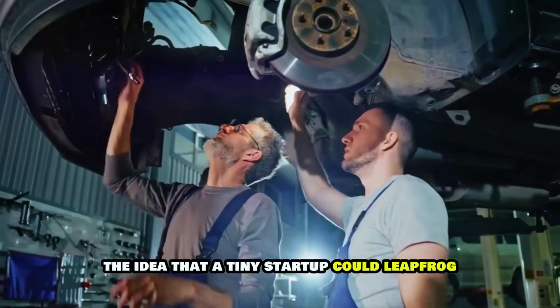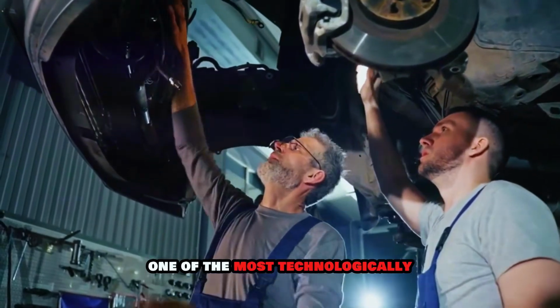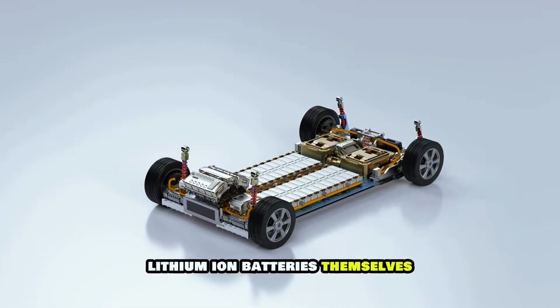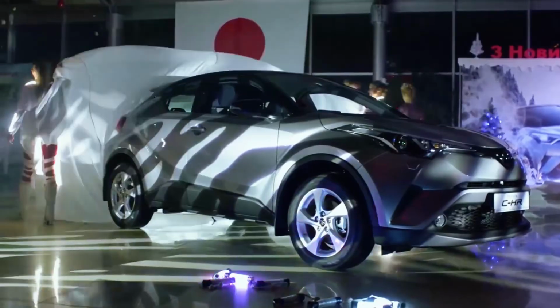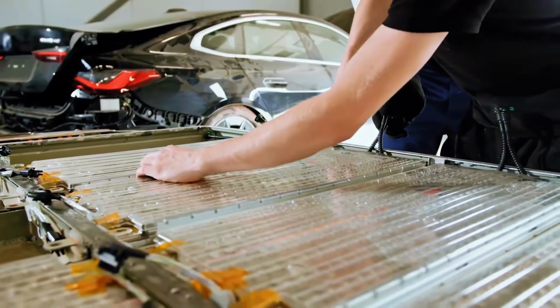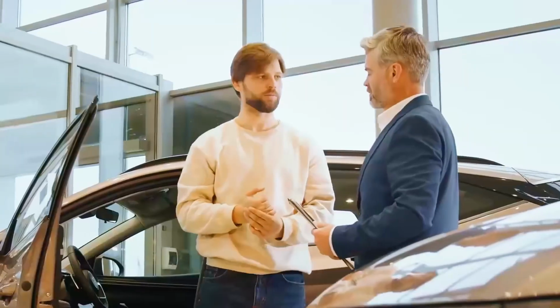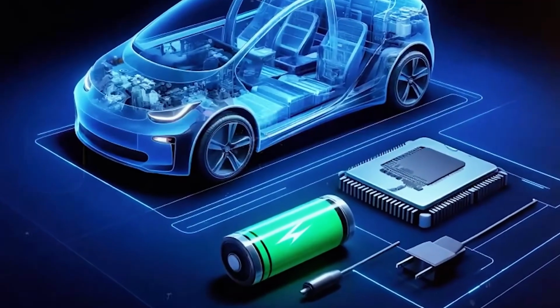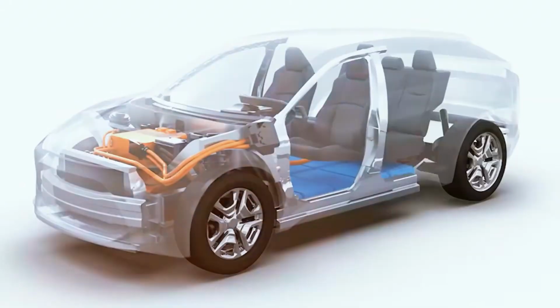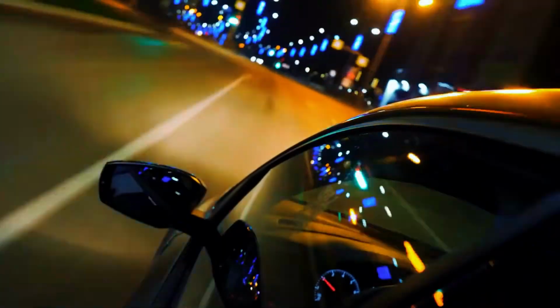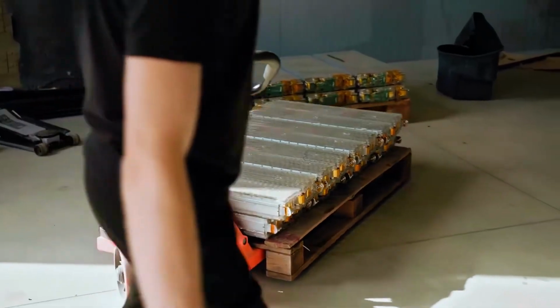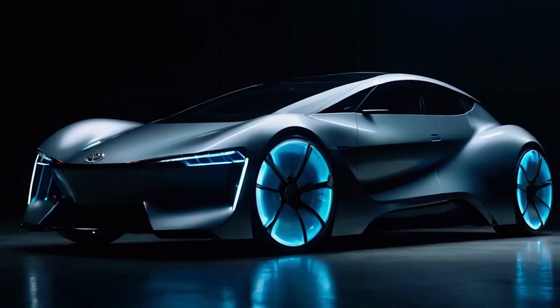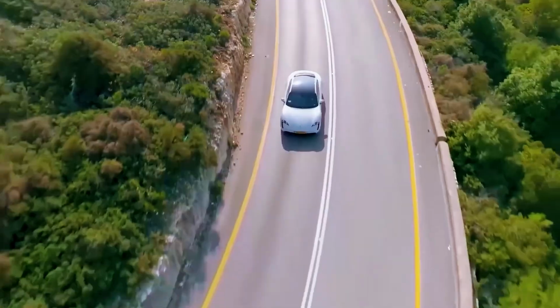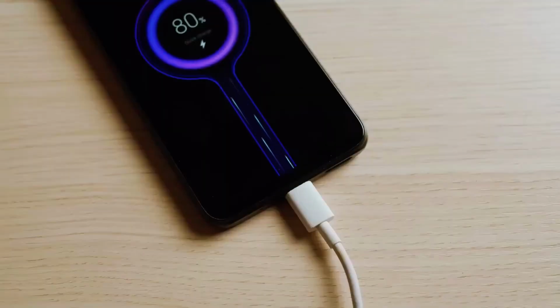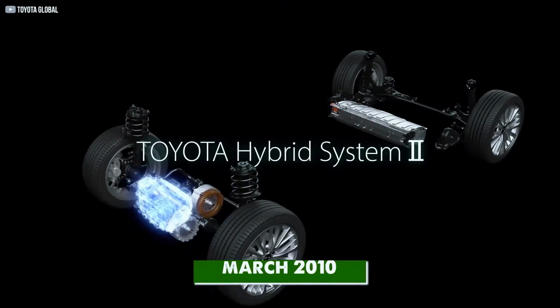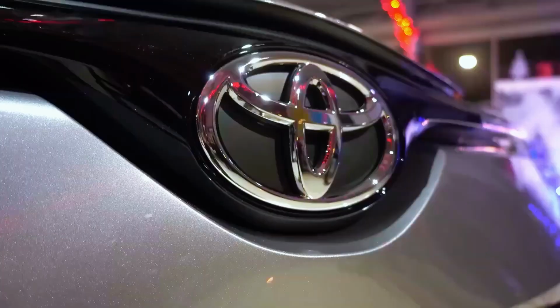Pair a lithium metal anode with a solid electrolyte and a high-voltage cathode, and you have a cell capable of reaching 400 to 500 watt-hours per kilogram. At the pack level, because solid-state designs require dramatically reduced thermal management hardware, real-world energy density could reach 300 to 400 watt-hours per kilogram. That is roughly double what today's best lithium-ion packs deliver: double the energy in the same weight, or the same energy in half the weight. Either way, vehicle range, performance, and design flexibility change completely.